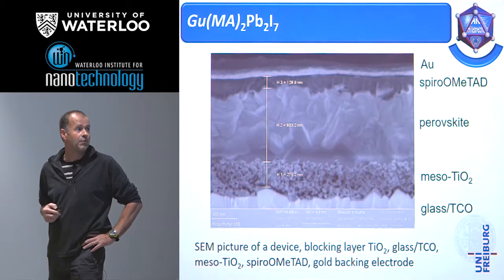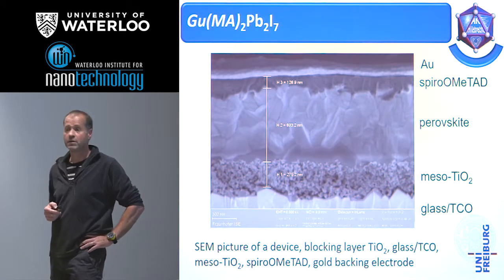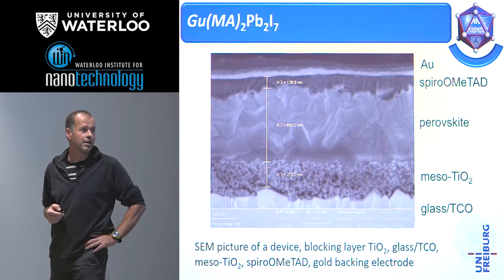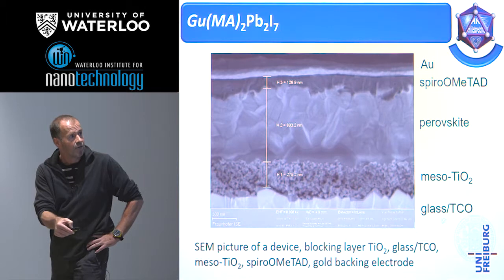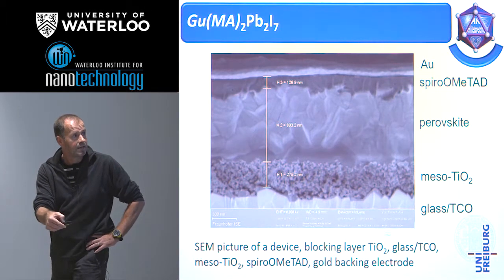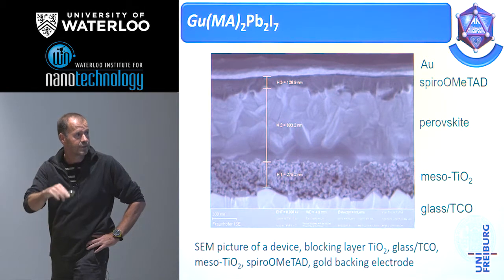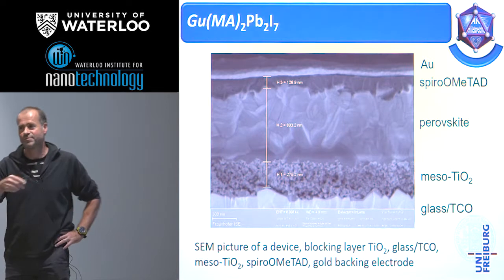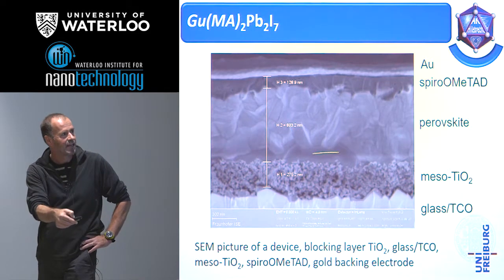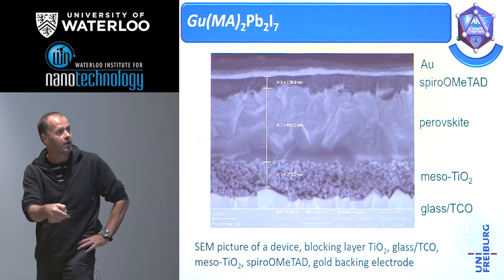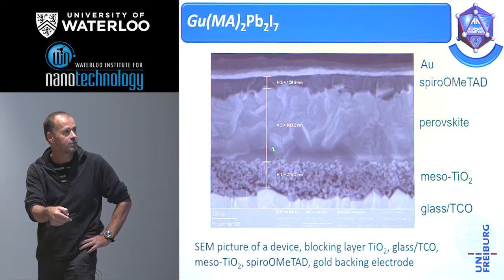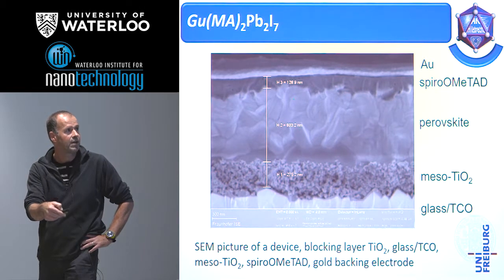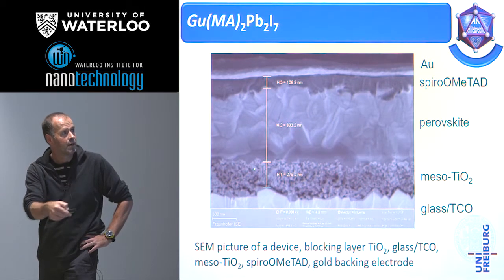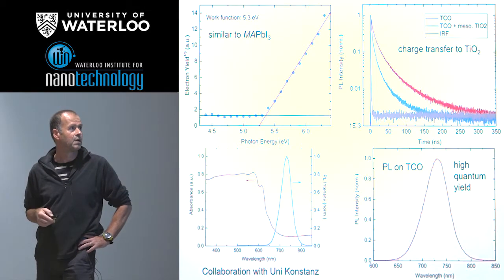We built up a device in collaboration with our colleagues from the Fraunhofer Institute for Solar Systems. That means we have a glassy substrate. We precipitate mesoporous titanium dioxide and our perovskite layer with a thickness of about 300 to 500 nanometers, something like that. Additionally, we add a p-conducting organic layer to get the charge separation, and we back it with a gold electrode. That's the complete device, and we could show that it really works.